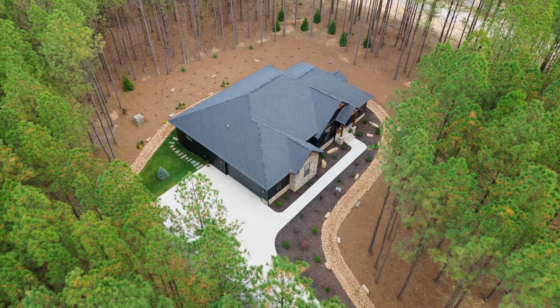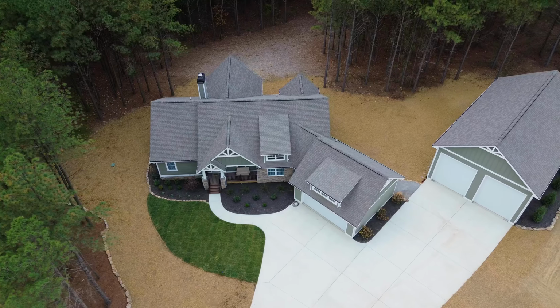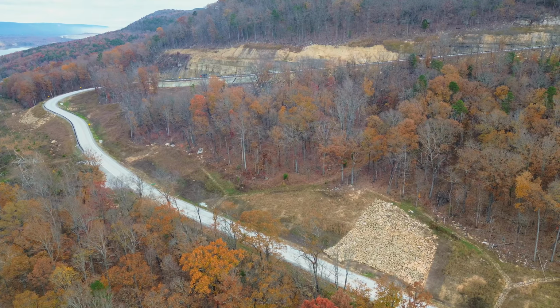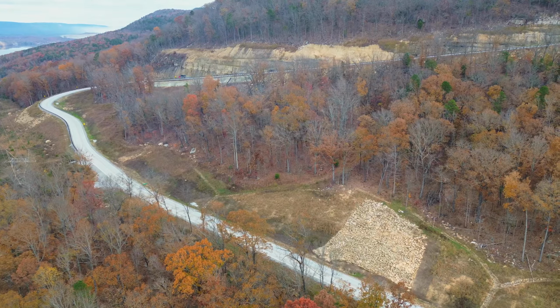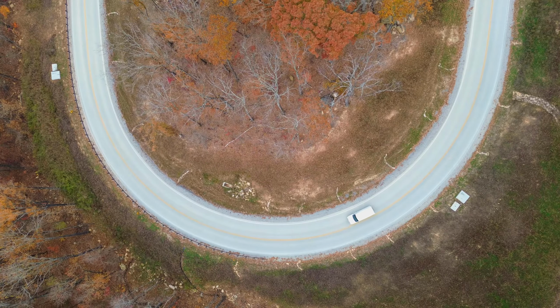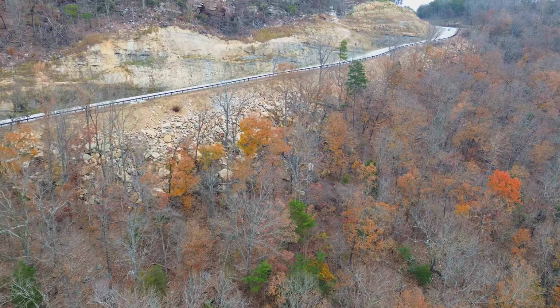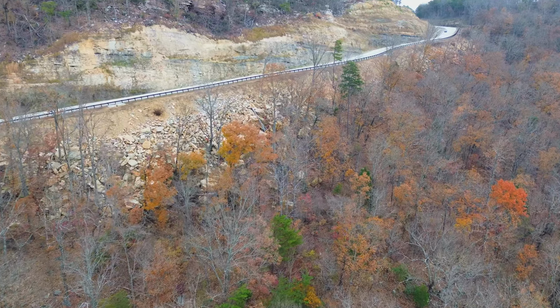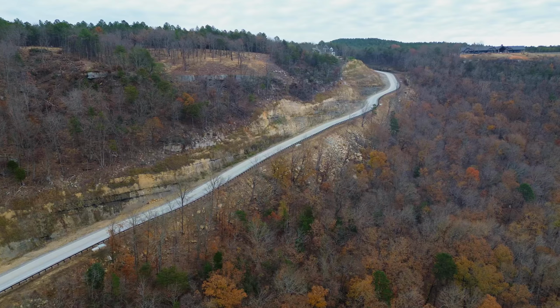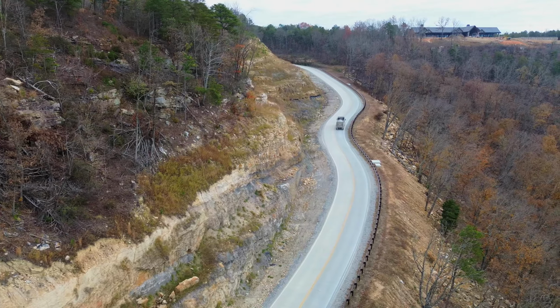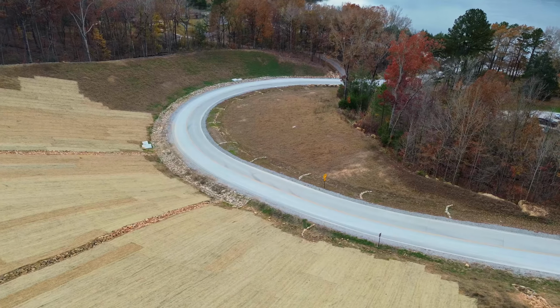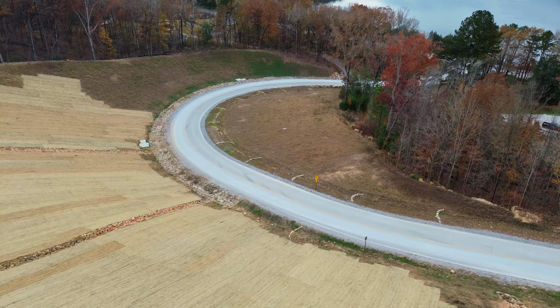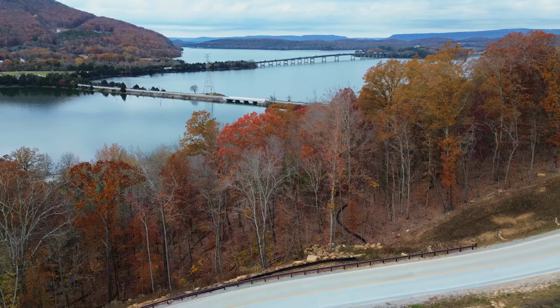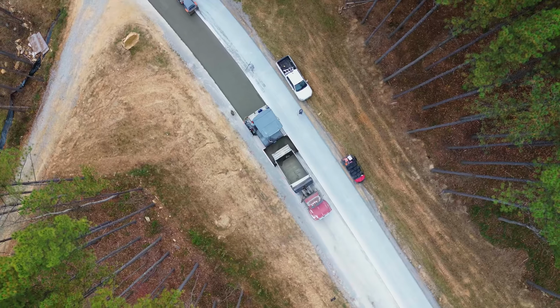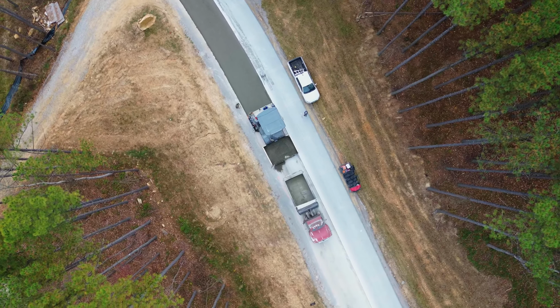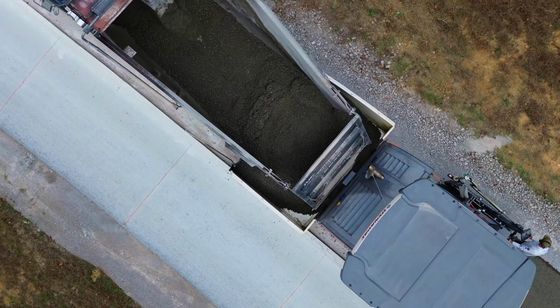This project, River Gorge Ranch, covers more than 7,000 acres. To reach every lot, normally, asphalt would be the default choice. The original plan called for 2 inches of hot mix asphalt over 6 inches of base material. But with a 6 to 7 year construction schedule and constant heavy truck traffic, the owner was concerned that the asphalt layer would deteriorate quickly. The owner wanted a durable pavement which could be placed and open to traffic quickly. RCC offered a stronger, longer-lasting, more economical approach.